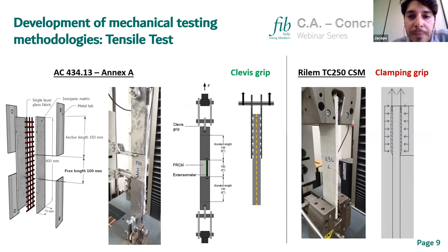And if we talk about the mechanical characterization of the material, this is quite a complex topic because the material is heterogeneous. So it is not so easy to characterize it in order to obtain the mechanical parameters that we then need in the design formulation. So these are the two main test setups to characterize the FRCM system in tension. So we have the AC 434, the American guidelines, that provides a clevis grip anchor to grip the specimen and to test it in tension.